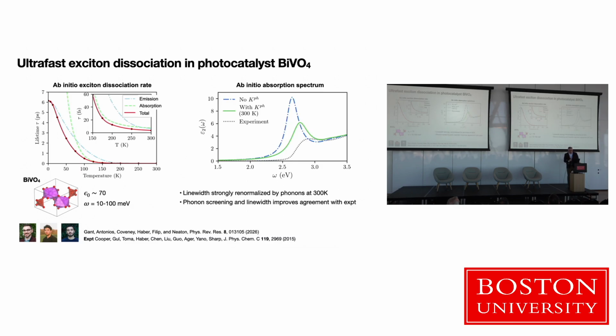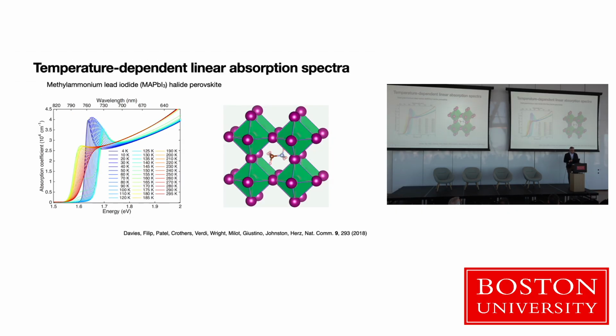And then this has a consequence for observables, and let me say a couple of comments about that. So this is an optical absorption spectrum. It's a linear absorption spectrum for this system. And so you can see if you introduce these finite temperature effects, the absorption spectrum gets a little bit closer to the experimental spectrum. But without the finite temperature effects, you have this very strong exciton peak, which isn't seen. So it's not a perfect agreement, but I think it shows you the impact of including these effects.